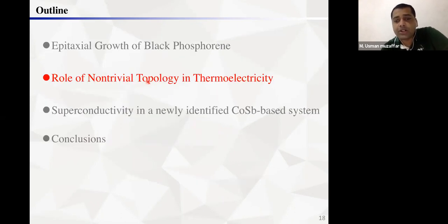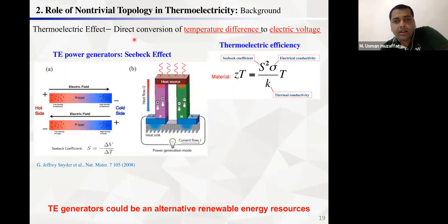So the next is related to the role of non-trivial topology in thermoelectricity. We know that, consider we have a semiconducting material, and when we create a temperature difference across the material, it creates a potential difference. This potential difference is known as the Seebeck effect, and how much potential difference is created per one Kelvin of temperature difference is known as the Seebeck coefficient. So the efficiency of a thermoelectric material can be mainly judged by using this formula. This formula consists of 3 parameters. The first is the Seebeck coefficient, then the electrical conductivity. This one corresponds to the Seebeck coefficient, this one corresponds to the electrical conductivity, and K is the thermal conductivity.